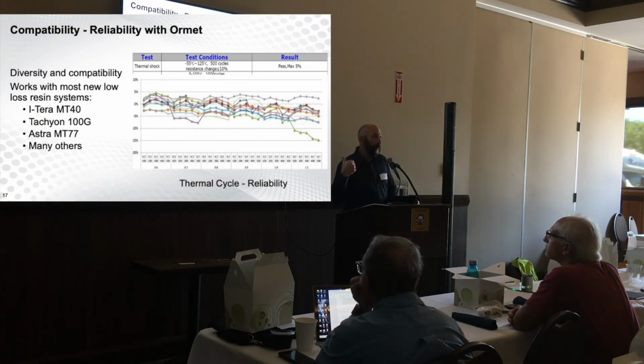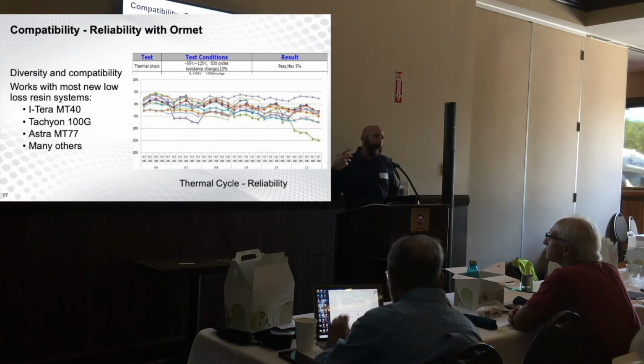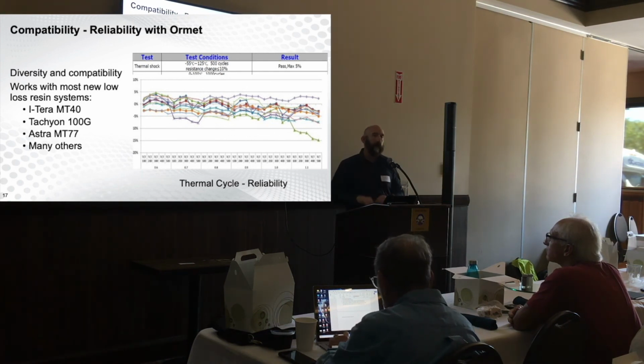So we've had some very good reliability testing with Ormet. We're still trying to get more data, but again, with the Ormet paste, you get rid of that electroless bond layer between your electrolytic copper and your foil copper. So the potential for some really good reliability gains.